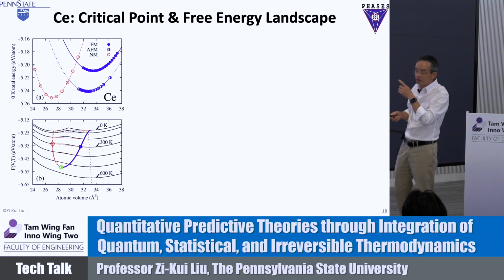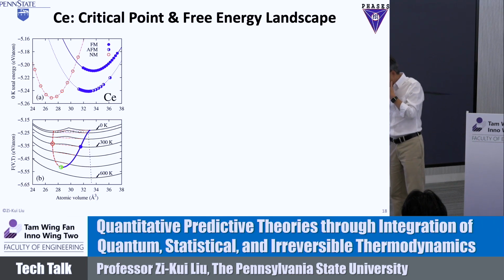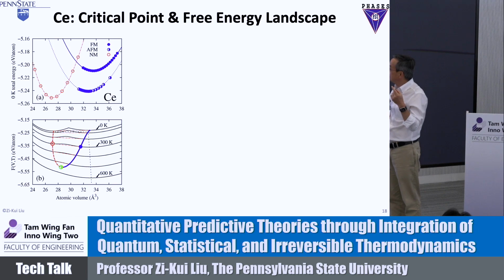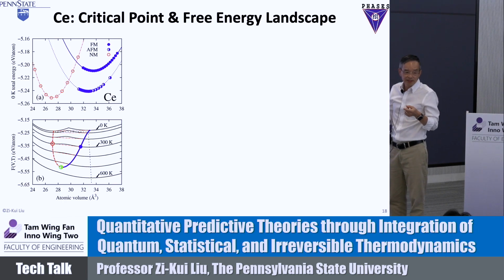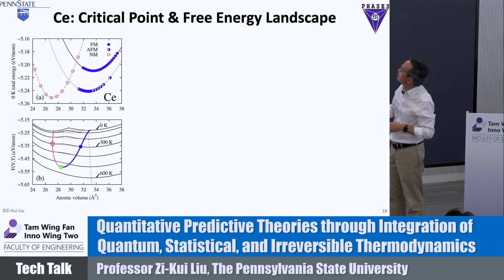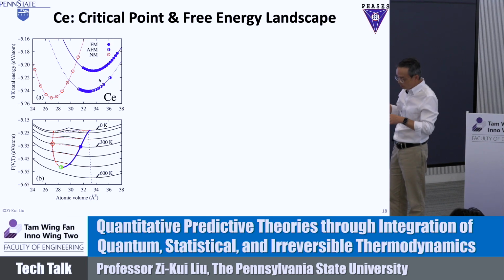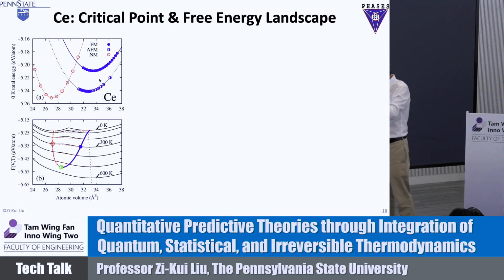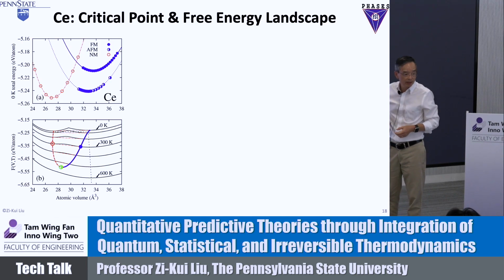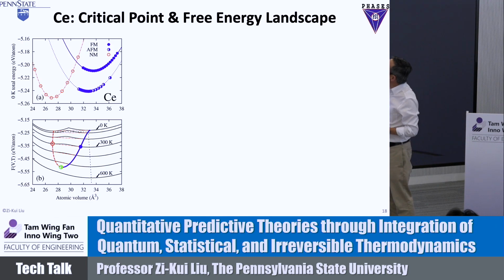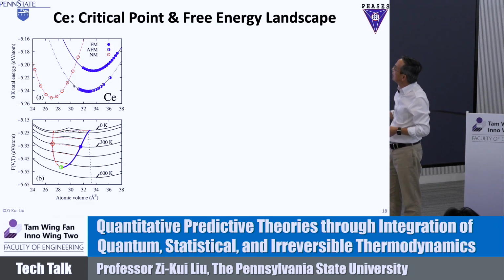So we did an example, cerium. Cerium is the only element on the periodic table which is non-magnetic at 0 Kelvin and becomes magnetic at high temperature. You can do a 0 Kelvin calculation. You can see that the red line is non-magnetic; the EV curve has the lowest energy. At high temperature, it becomes ferromagnetic. There's a blue dot here. But of course, between the ferromagnetic and the non-magnetic states you get the anti-ferromagnetic one, so the half-filled symbol here is the anti-ferromagnetic configuration.